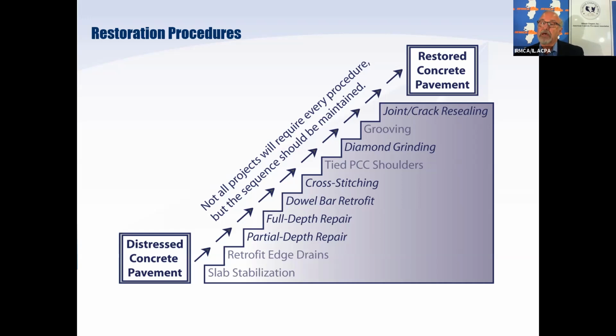If we have some type of a drainage issue that we've identified as driving the distresses, we can retrofit edge drains on very much any pavement that's out there. But now we get up to the more common types of repairs. Partial depths, full depths. Those are done more than anything else with the exception of diamond grinding.